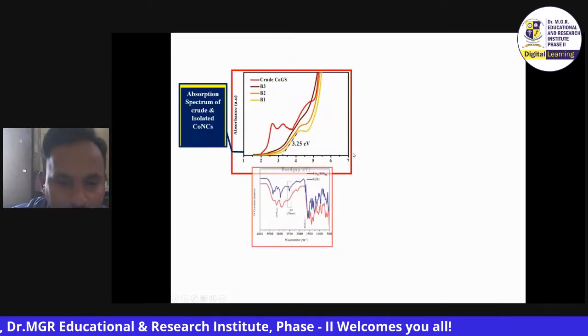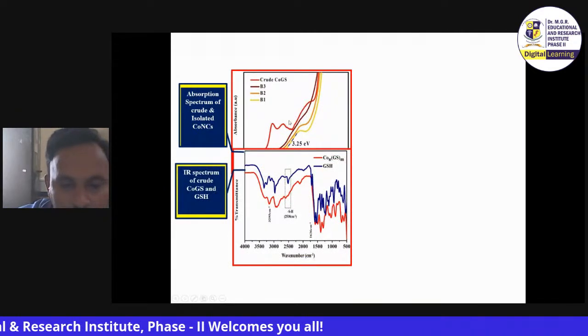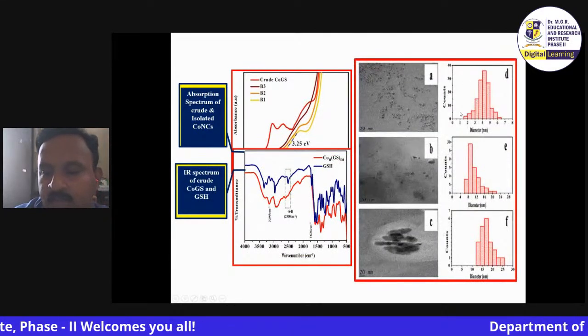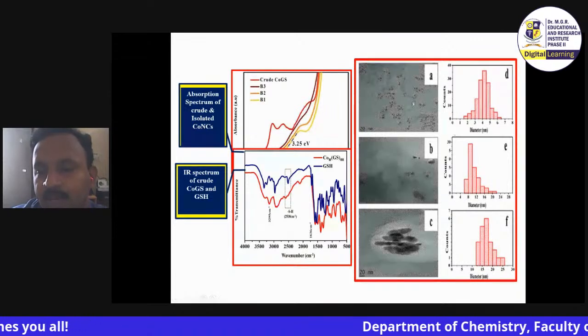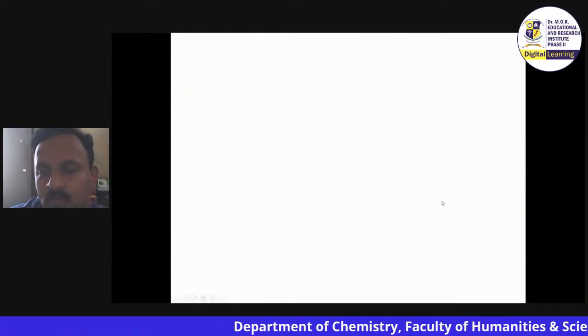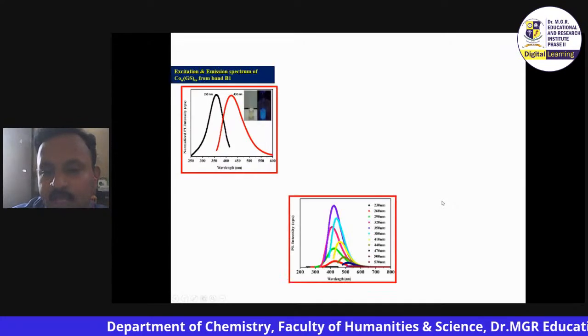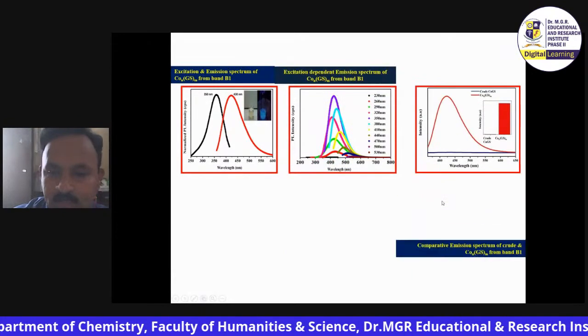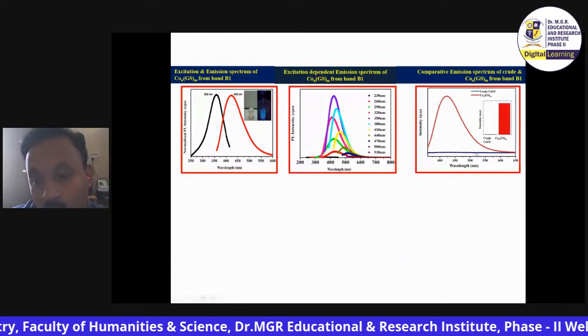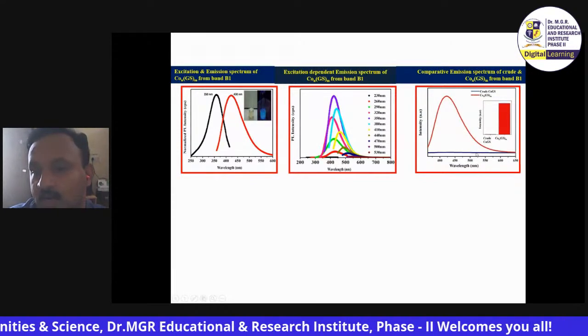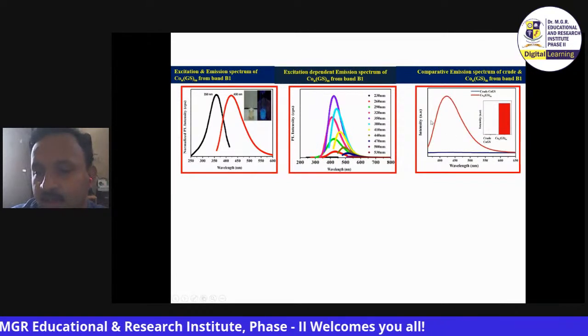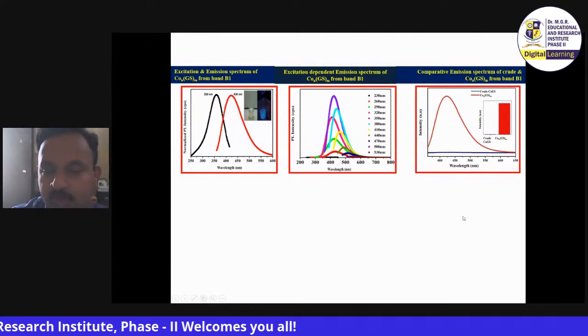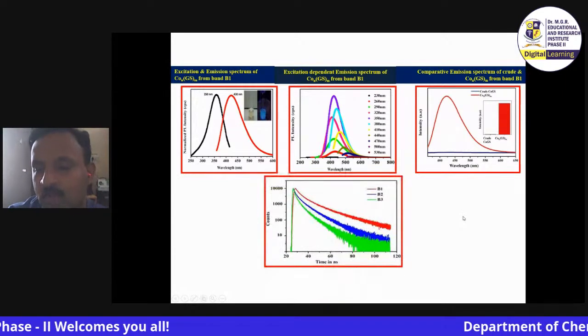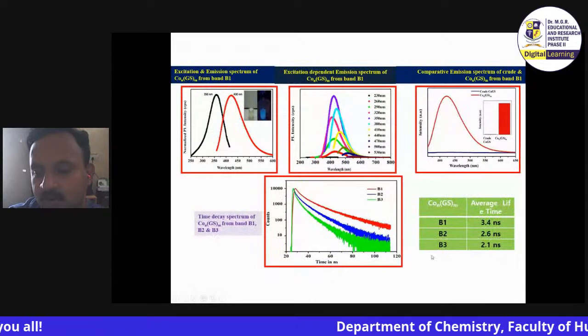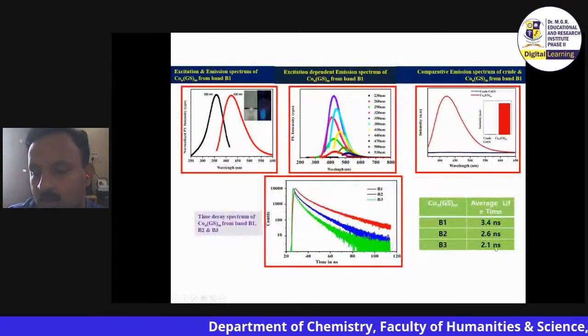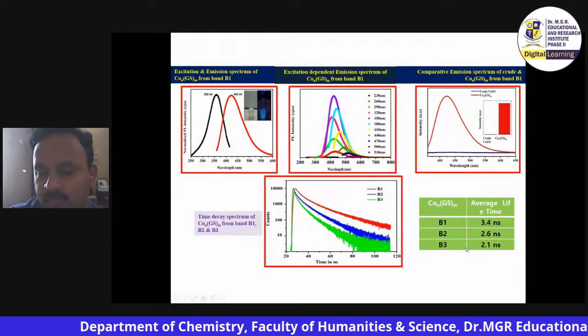These are the absorption patterns. The bands had different absorption patterns, and you can see the size also varies. So different bands had different sizes, and our aim should be towards highly monodispersed particles. You can see that a crude particle had no photoluminescence for the cobalt cluster, but a PAGE-separated cluster gave photoluminescence. That is the success of this paper. It has been published with a blue emission, and it had different lifetimes, the transition timing also.